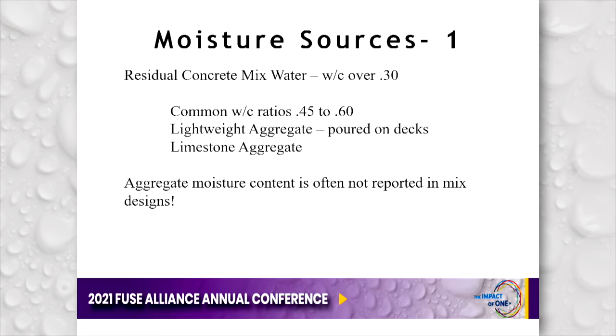But there are other places that you may not be aware of. We look to lightweight aggregate concrete. That lightweight aggregate is typically what's poured on a deck, and the lightweight aggregate in the mix design will be in a saturated condition. That's typically going to be 10% to 30% of the reported weight actually being water, but not reported as water. That also has to dry, but is very slow.